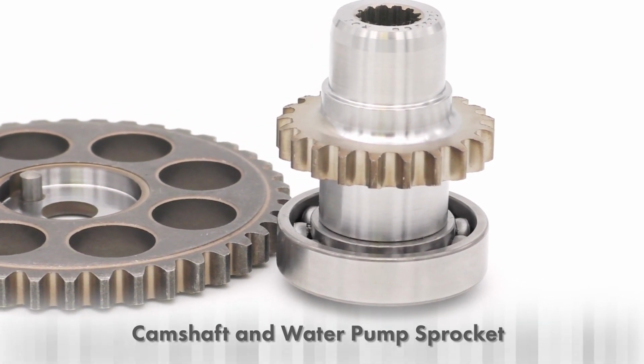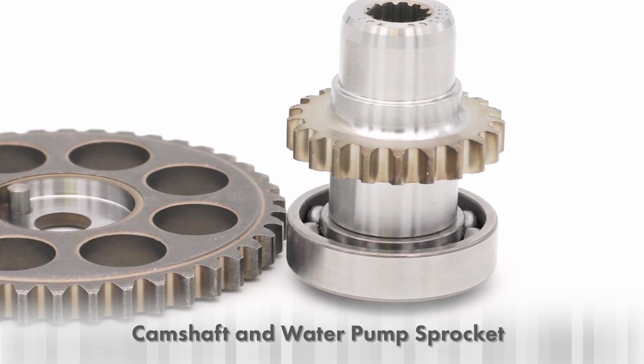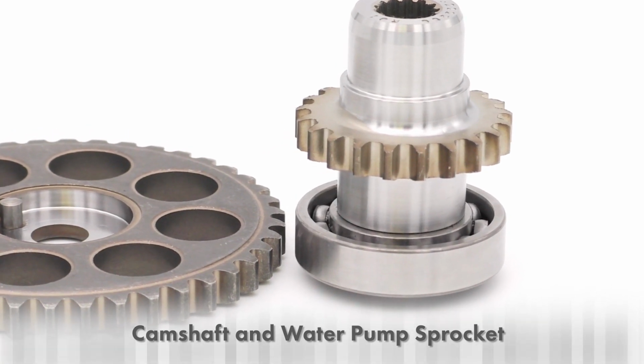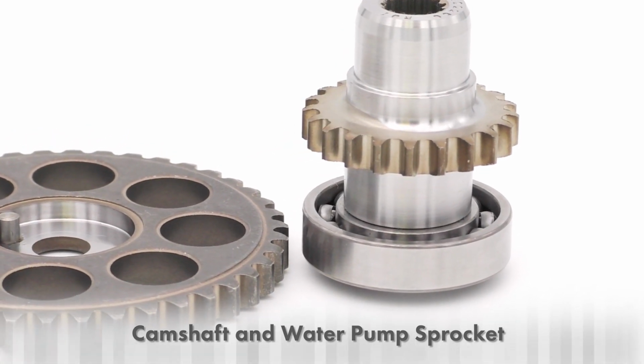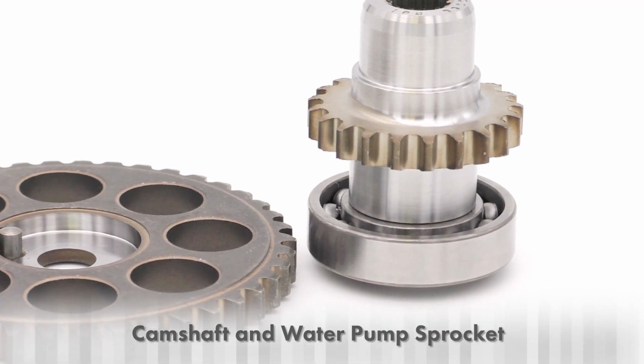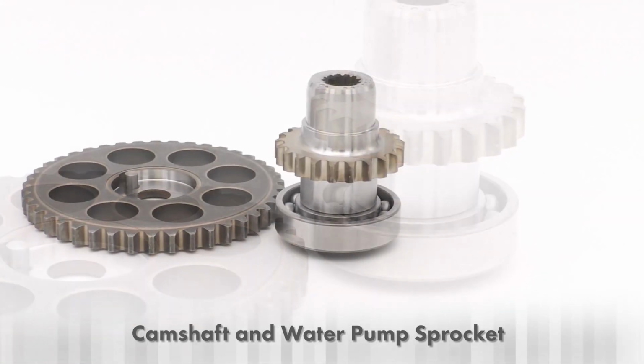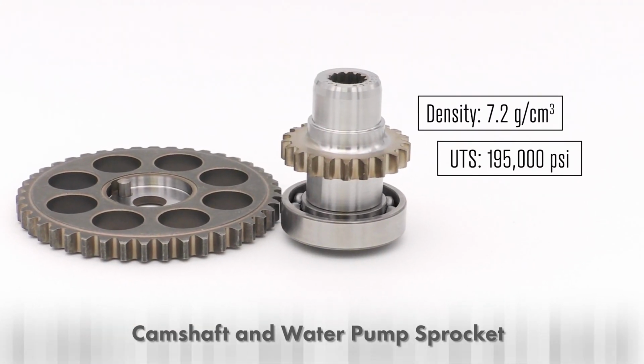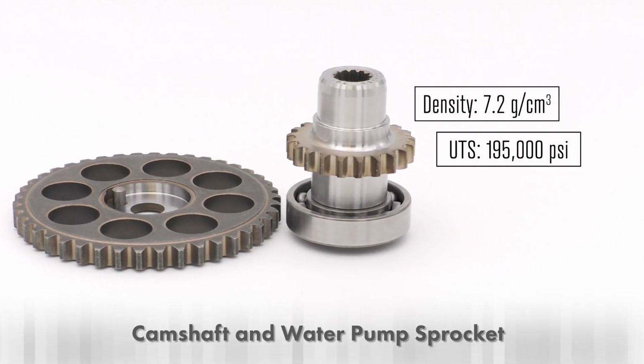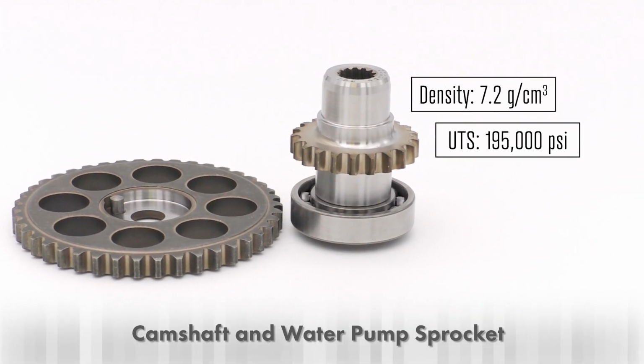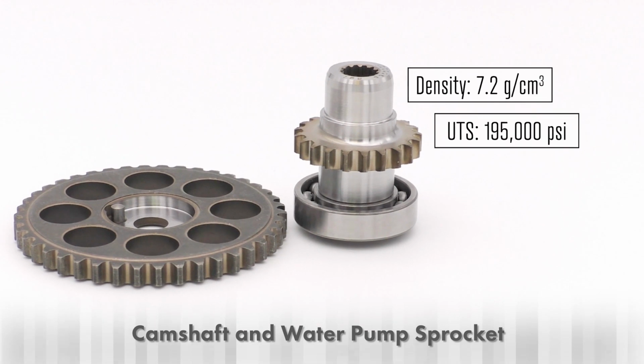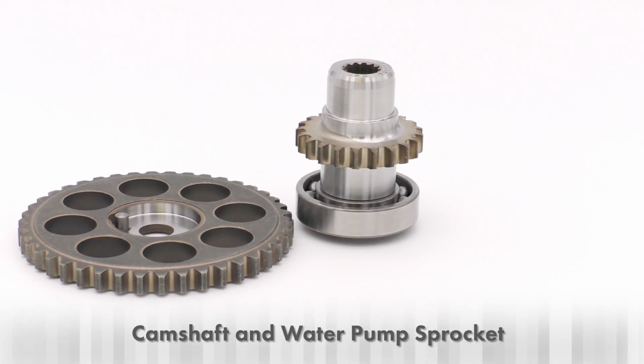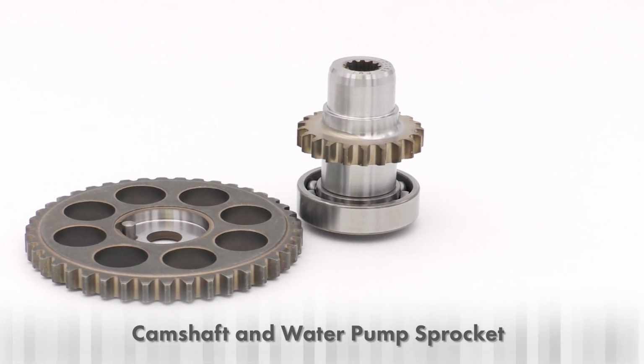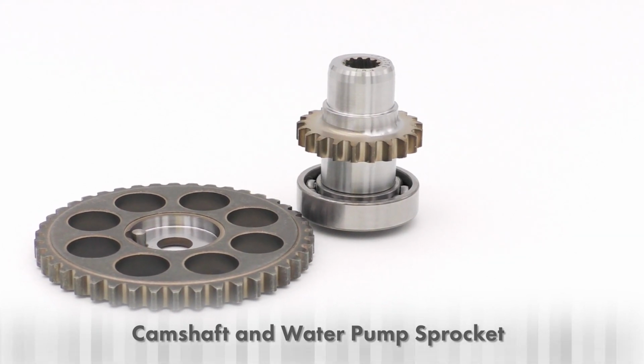The parts are made from a modified 4300 low-alloy steel powder that is warm die compacted and high-temperature vacuum sintered to a typical density of 7.2 grams per cubic centimeter, giving an ultimate tensile strength of 195,000 psi, nearly 2% elongation, and an apparent hardness of 45 HRC. The PM components represent a 40% cost savings compared with machining.